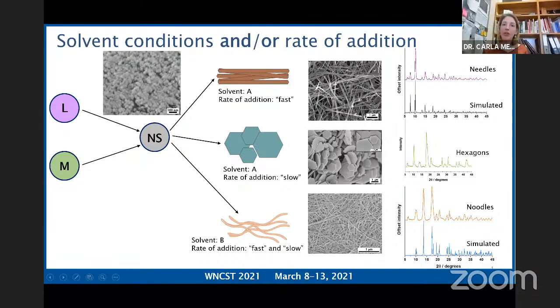And hopefully now we can go back and use this information. While rate of addition didn't seem to have an effect on ZIF8, if we were to have only studied this MOF here, rate of addition also would have seemed like it didn't have an effect on the resulting crystal structure or morphology or anything else. But in fact, with different solvent conditions, the rate of addition can have very significant differences.